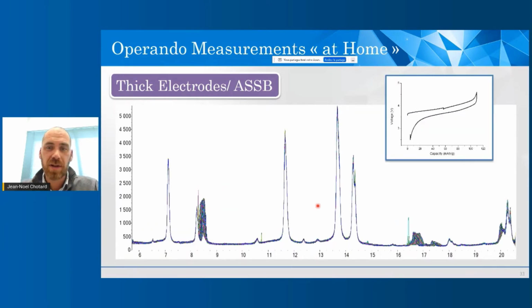And we applied that also to studying all solid-state batteries and cycling them directly also into the diffractometer. So that's what we did here. And you have at the top right here the galvanostatic curve of this material. And as you can see, only a few peaks are moving right here and there. That's the active material. And in fact, all the other peaks belong either to the cell itself, the windows, or the solid electrolyte. And in fact, we don't want the solid electrolyte to move because this material should not be electrochemically active. So during the cycling, this should not move at all. And this is what we observed, so we were quite happy about that.